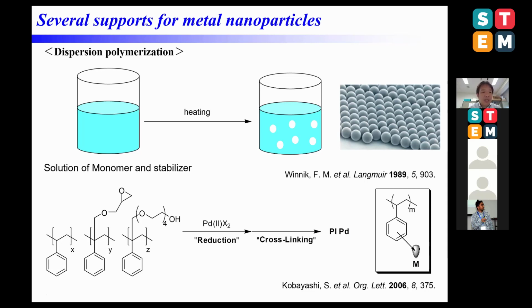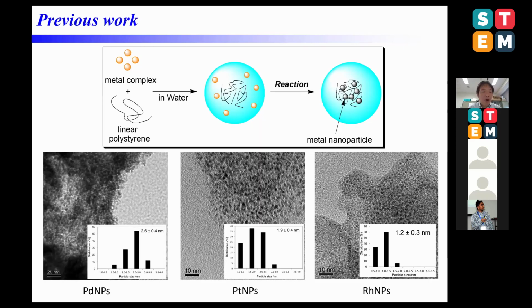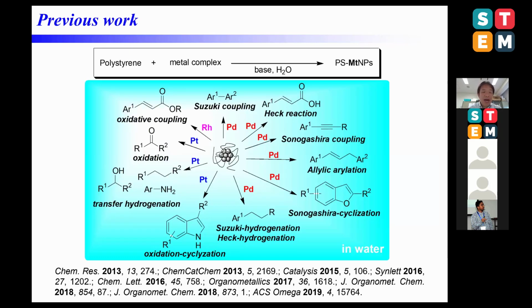Based on the idea that metal nanoparticles with a fairly uniform size will be stabilized on polymer supports by hydrophobic interactions in water, our group successfully developed linear polystyrene-stabilized palladium, platinum, and rhodium nanoparticles. And they have high catalytic activity for these reactions and reusability, as shown here. Although we developed the effective reusable nanoparticle catalyst, as shown here, we thought they are difficult for industrial application because they are powders.